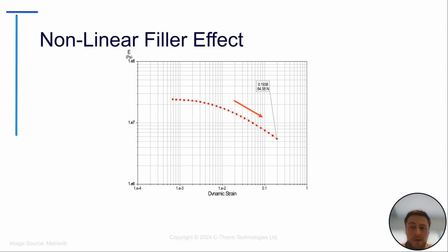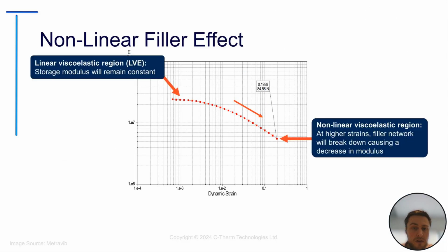And here's a plot showing how this will look. We can see that we have our linear region at the start, at the small strains on the left of our plot. This is where the storage modulus will remain constant. And then after incrementally applying larger and larger strains, we'll start to enter the nonlinear viscoelastic region. This is where we notice that the stiffness or the modulus begins to decrease with a steep slope. This is one of the benefits of a high force DMA, that you're able to apply enough strain to your material to measure this. I just took a quick snapshot of this test, and you needed about 85 newtons peak to peak to be able to strain this material to get into that nonlinear viscoelastic range.